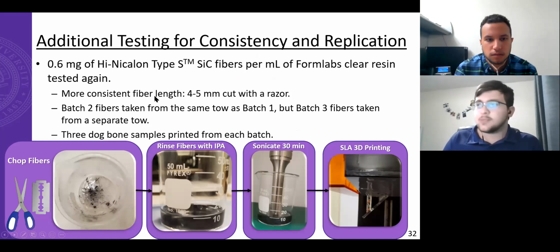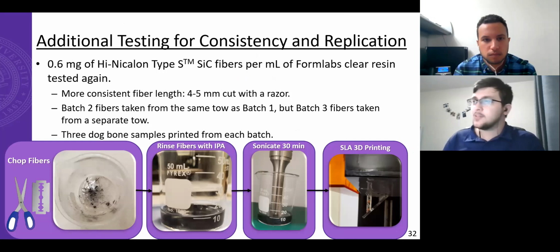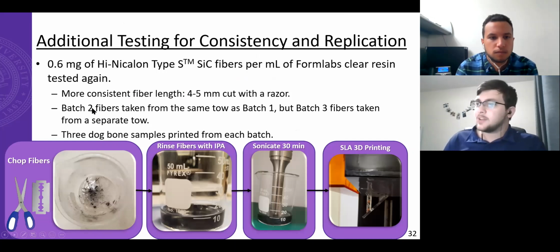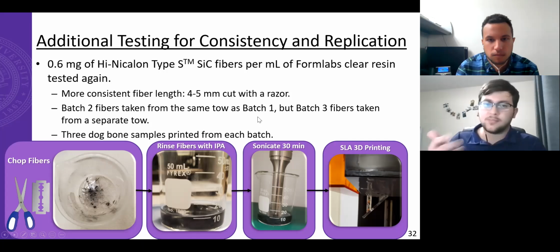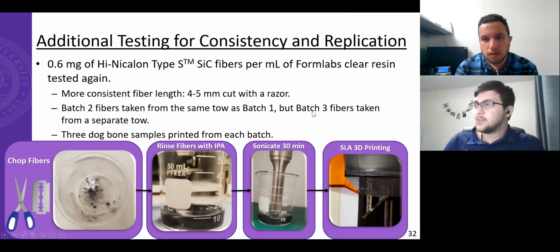For these batches, I did a more consistent fiber length because it was also brought up to me to try to do that. So we used 4 to 5 millimeters using a razor similar to this right here against a ruler. I say 4 to 5. I was aiming for 4, but I will say that not every single one was likely 4 millimeters in length. And then the batch 2 fibers were taken from the same tow. I think that's the same spool as batch 1. And batch 3 was taken from a separate tow and a separate spool. And then 3 dog bone samples were printed from each of these batches, and the same procedure was done.